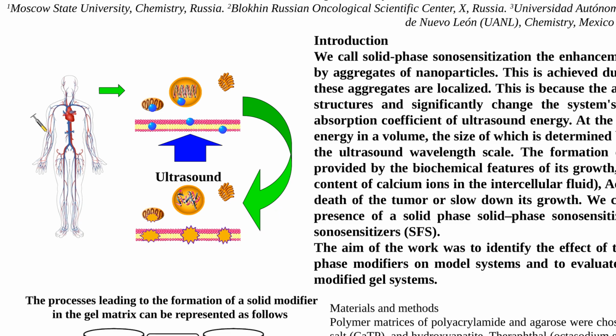In a tumor, the formation of nanoparticles and their aggregates can be promoted by biochemical features associated with tumor growth, including a low pH and an increased concentration of calcium ions in the intercellular fluid. The additional release of acoustic energy in these regions may contribute to tumor cell death or slow tumor growth. We refer to the phenomena underlying this approach as solid phase sonosensitization, and the nanoparticles and their aggregates as solid